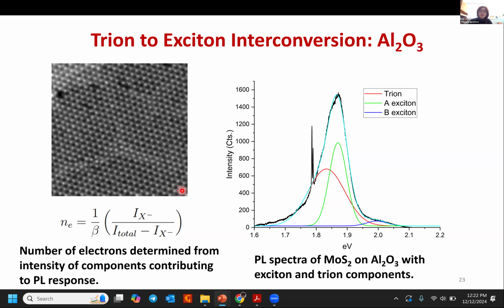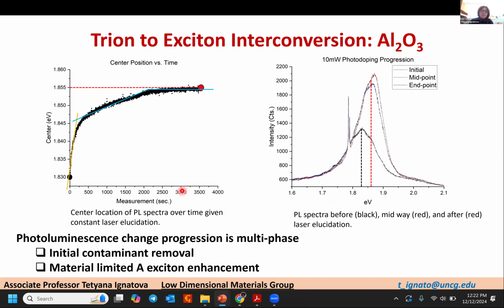What we did later on, we illuminated this sample with power which will not cause overheating, will not cause etching, and we traced the optical signature over a long period of time. You can see here on the left side the maximum center location of the photoluminescence spectra over a certain period of time. You can see that there is enhancement, significant enhancement, and this sample was not aged, it was a freshly grown sample. Enhancement, but with 3 slopes.